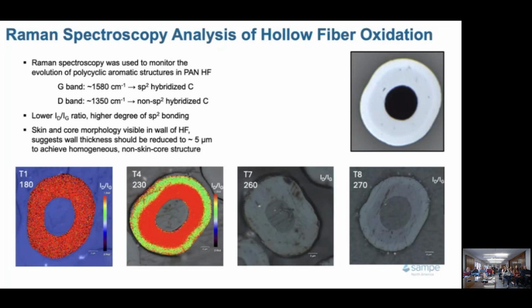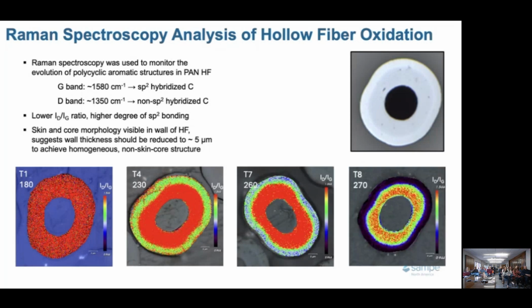We go to 230 and we start to see, in the Raman spatially right on top of the fiber, this area of increased conjugated bonding. Going to 260 it progresses, and after 270 it's progressed even more, but you still see quite a bit of red on the interior of these filaments, as at the very beginning. It's as if there is a limit to the size of the filament accessible for oxidation. This explains why carbon fibers are tiny in diameter, and suggests that we could, in fact, well-oxidize a hollow fiber if and only if we could produce it small enough, which is what we're working on.